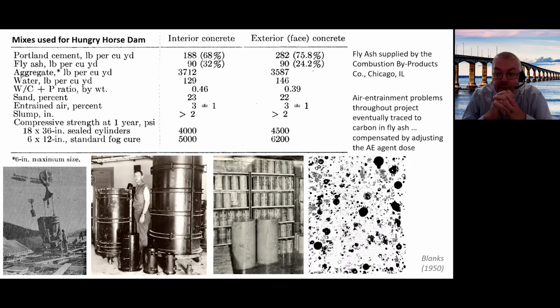If you look through some of the documentation on the use of fly ash in the structure, they did suffer a few air entraining problems, eventually traced to carbon in the fly ash, and they compensated for this by increasing the air entraining dose.